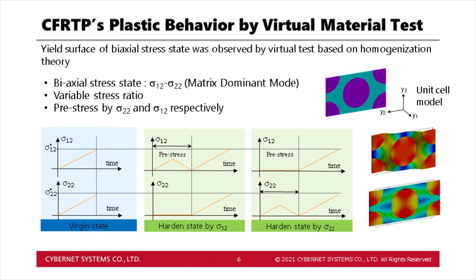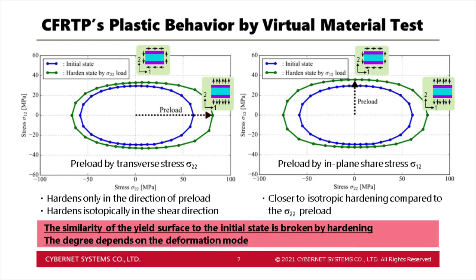In order to draw the yield surface, analysis was performed by varying the stress ratio of these two components. In order to observe the yield surface after hardening, the same tests were conducted for the pre-stressed condition. The pre-stress was tested for two cases, one with pure shearing and the other with uniaxial stress as shown in the green hashed area. This is the actual shape of the observed yield surface.